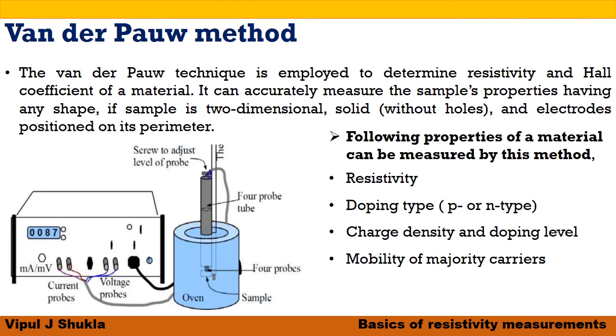In the van der Pauw method, it uses 4-point probes positioned around the perimeter of the sample rather than in a straight line. Therefore, this method measures the average resistivity of the sample, while the linear arrangement measures resistivity only in the measuring direction. The difference is crucial in anisotropic materials, which can be efficiently characterized by the Montgomery method.